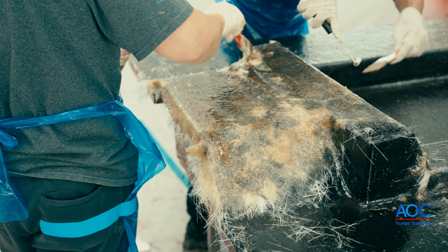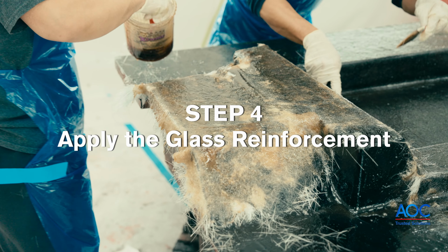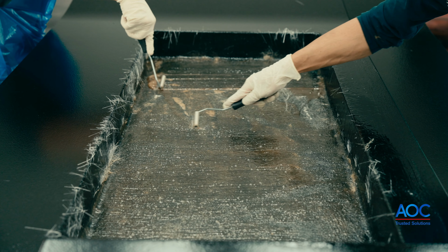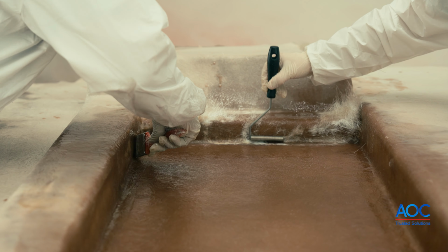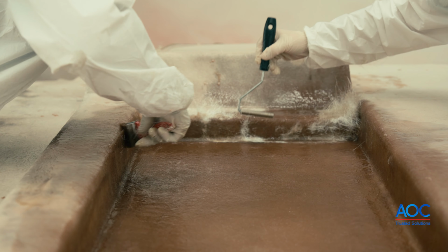Multiple layers of glass will be needed. The number of layers will depend on how thick the finished tool should be. Each layer will consist of 3 to 5 ply 1.5 ounce fiberglass, with ply thickness depending on the resin gel time selected. Build the laminate thickness by adding more layers of glass to the tool and rolling the resin on.